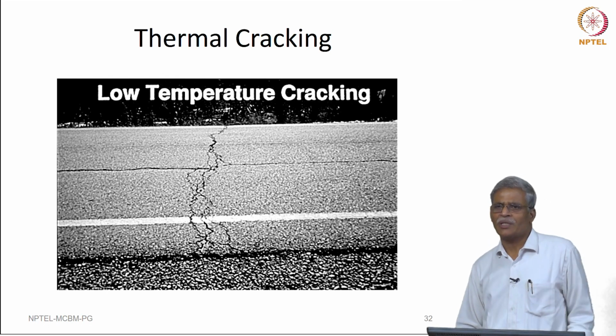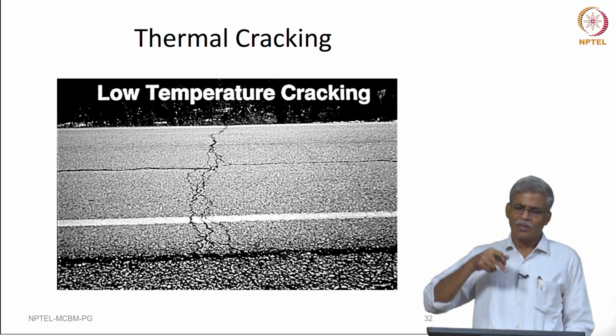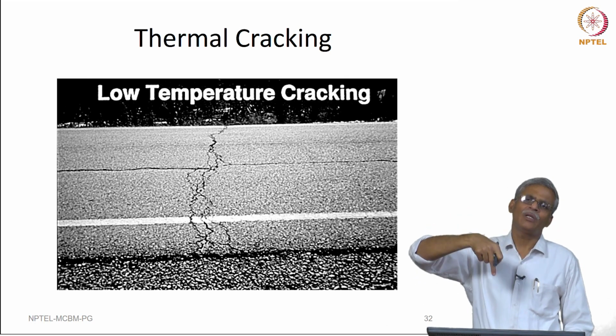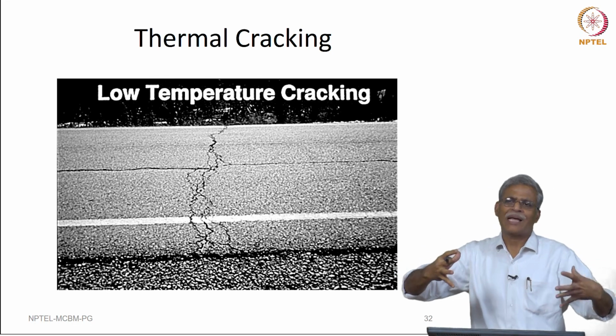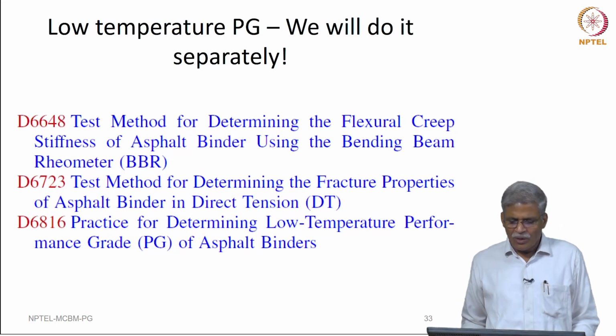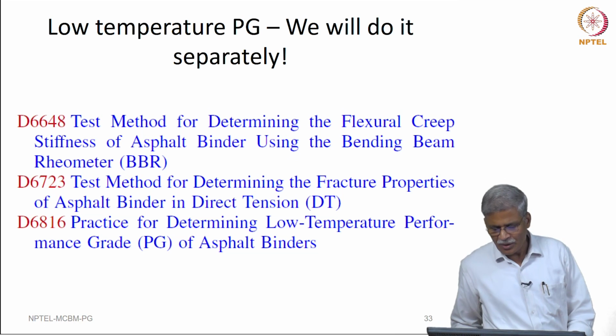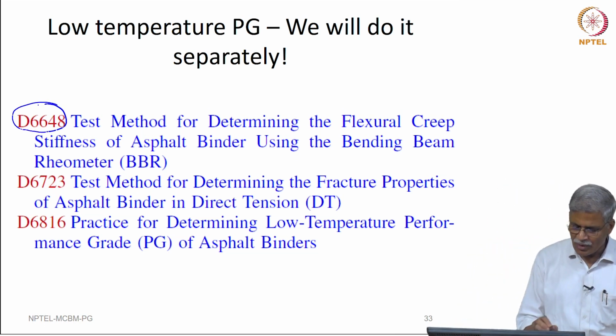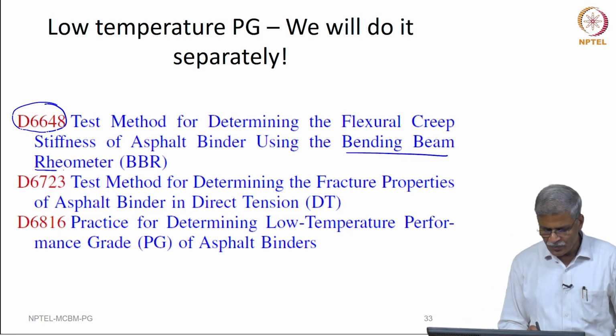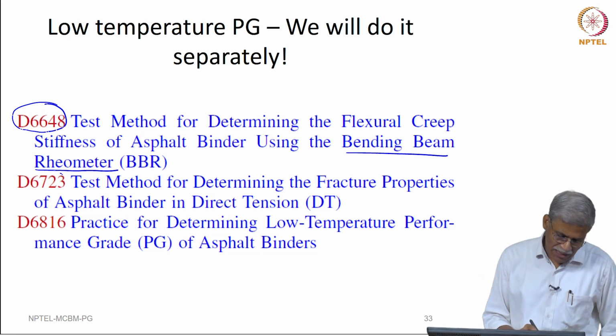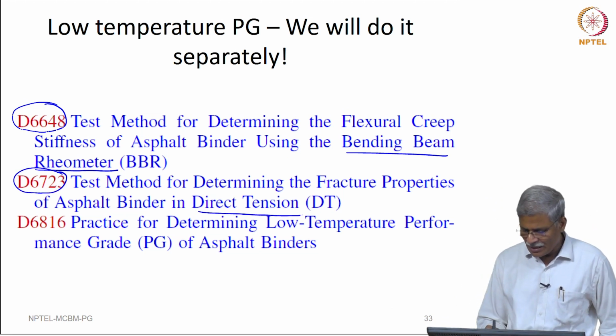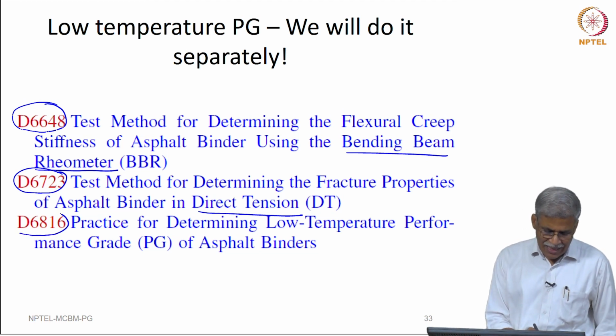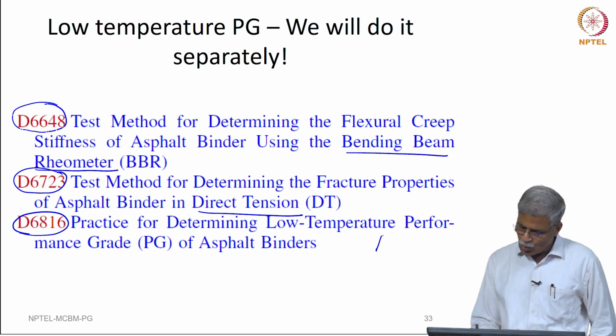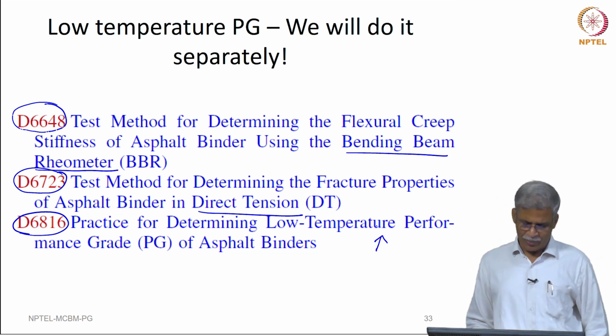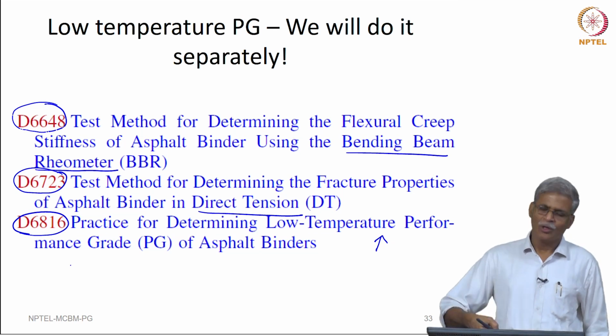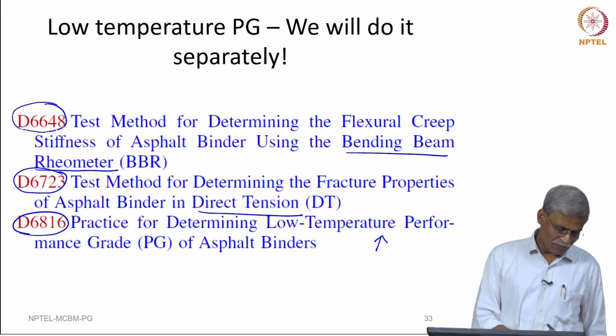And you have seen this picture earlier, but again it is good to revisit these pictures because this low temperature cracking is typically perpendicular to the flow of traffic, more or less like you are going to see cracks in blocks, right. Now, these are the test methods that are available as of now. One is D6648, which uses the bending beam rheometer, okay. Then there is another one, D6723, which talks about direct tension, and very recently D6816 has been introduced, which tells you how to use these ideas and pick the low temperature grade of asphalt binders. So, all these three will be discussed in detail separately, okay.